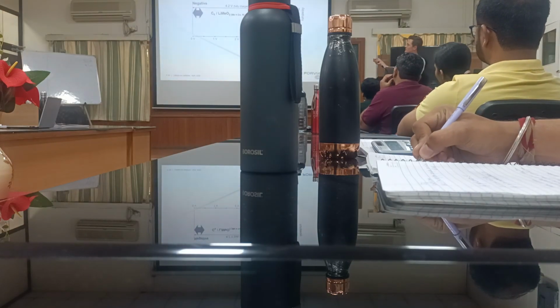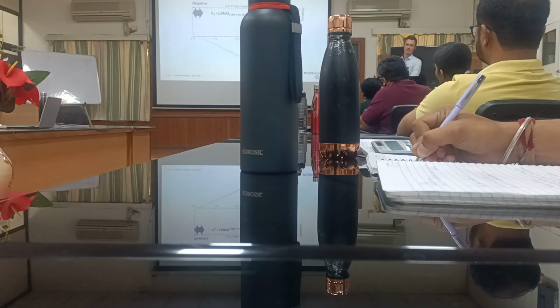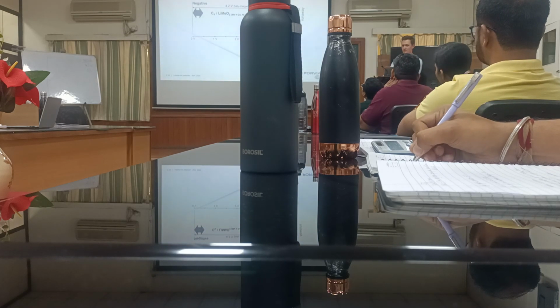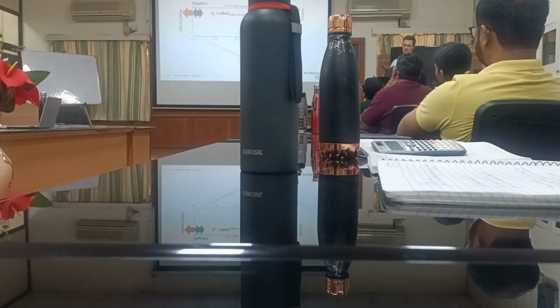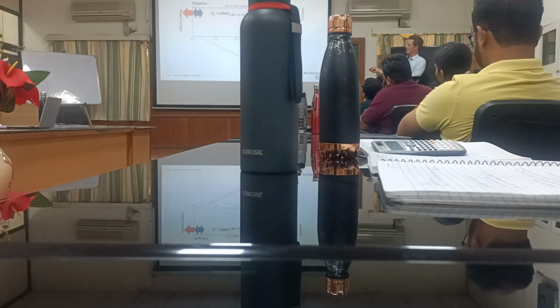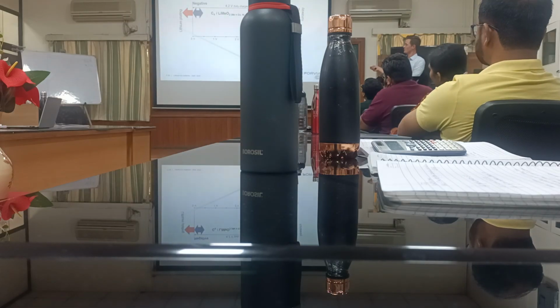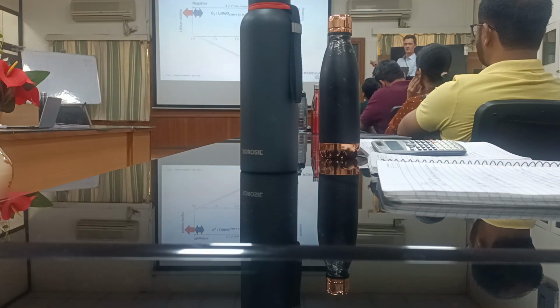Above 4.2 what happens is electrolyte decomposition, and that usually leads to a thermal runaway. And below 0 volt, what happens? Electrochemically, it is more favorable to produce lithium metal instead of lithium ions. So you can remember, whenever your lower potential drops below 0, you will always destroy your battery cell. And it is important for many applications. We will talk about it several more times today. It's called lithium plating.